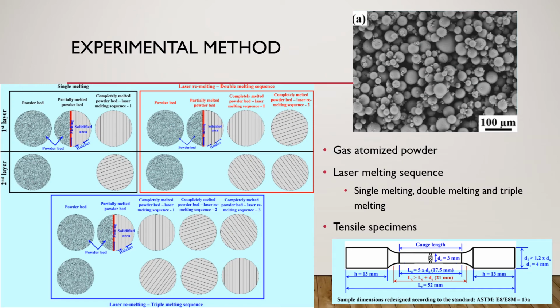For the experiments, gas atomized powder was used. The right top corner picture shows that these powder particles have a spherical shape, although there are several satellites attached to the powder particles. The laser melting sequence can be observed on the left bottom picture, where the single melting is when the laser scans the powder very selectively once, so after the melt pool solidifies, the next layer of powder is deposited and the process iterates until it is done.